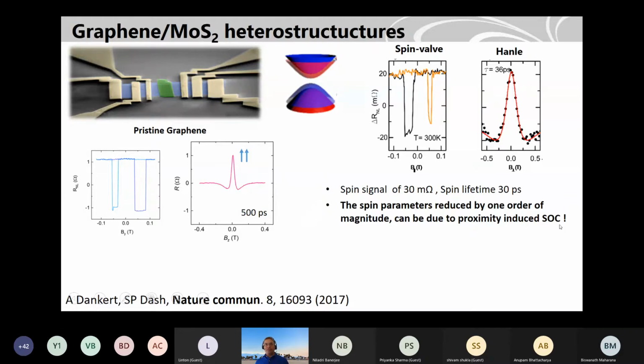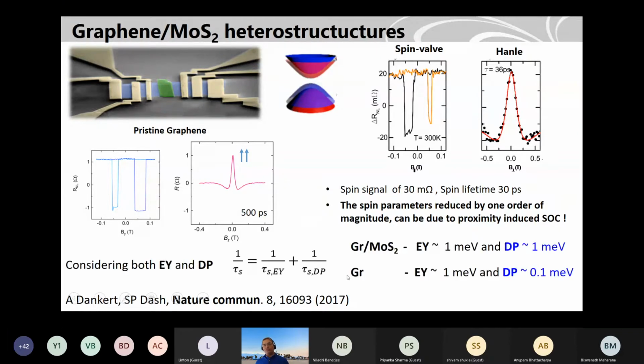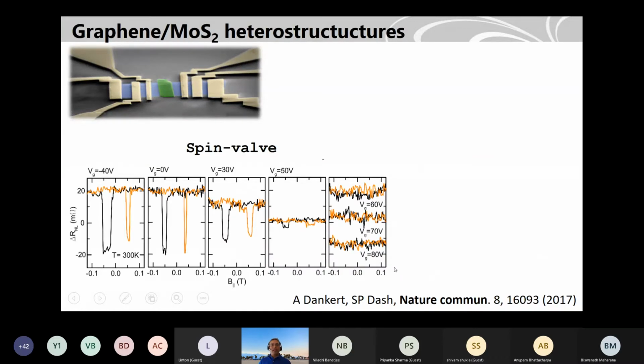So this reduction can be due to different things, but it can also be due to proximity induced spin orbit coupling. If we assume proximity induced spin orbit coupling, we find that the Elliott-Yafet mechanism, which is due to momentum scattering, remains almost the same, but the spin orbit term went up by an order of magnitude. This is 0.1 millielectron volt for only graphene, and for the heterostructure it is around 1 millielectron volt. This is also supported by theoretical calculations, which estimate a similar order of magnitude.